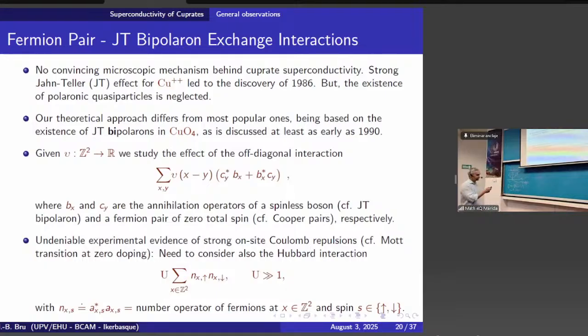In our case, the bipolaron was always there, but there are big communities that don't want to do this. So as I said, our guess is to use this to explain the functioning of this exchange interaction. And another ingredient which is really important: these cuprates are Mott insulators. If they are Mott insulators, it's a strong indication that there is a strong Hubbard repulsion. So Hubbard repulsion should not be neglected. You should not say everything is quasi-free; you need to take into account the Hubbard repulsion. That's something that you cannot avoid.